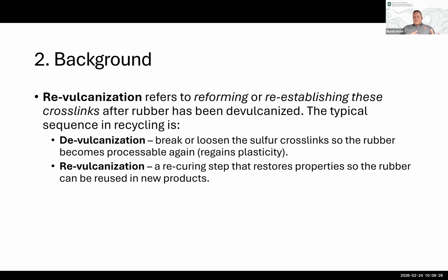When it comes to re-vulcanization, typically how that's done is through what we call devulcanization. When we say vulcanize, you could think of it as sulfurize. We're adding sulfur to the rubber, and that's what helps make those chains and a sort of net effect, if we were thinking of spaghetti noodles. So to revulcanize, first we have to take those chains that were present in the original rubber and break them apart. So we devulcanize and then re-vulcanize to try and get those chains back together so we can have a nice strong rubber.